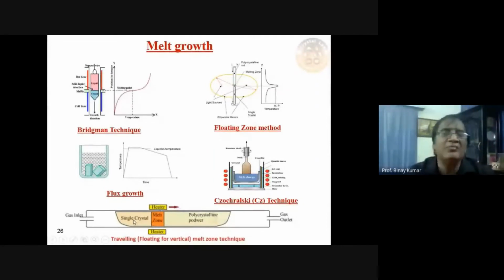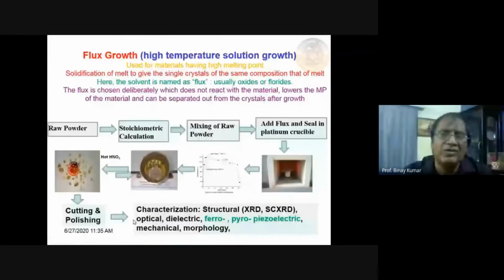Now come to the flux growth technique. What we do in the flux growth technique is first take the material, make a stoichiometric calculation and a specific ratio of different constituent atoms, then mix it, then add a flux. I will explain a little bit what flux is, and then put it inside a furnace, which in our case is normally around 1100 to 1400 degrees. Then give a proper temperature profile.